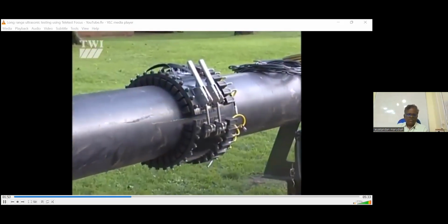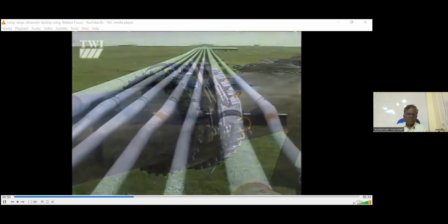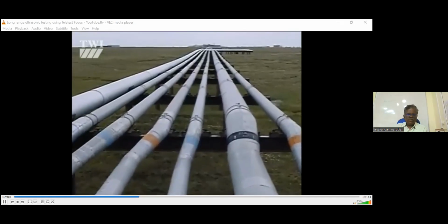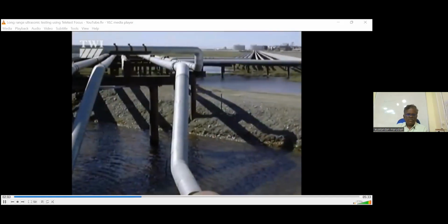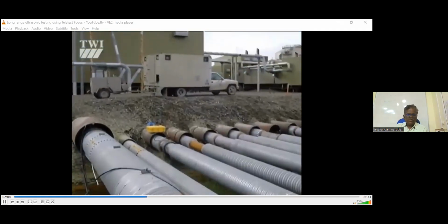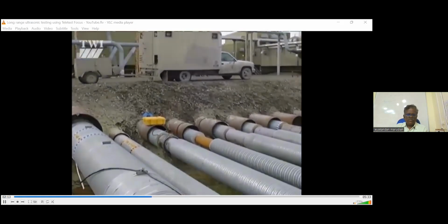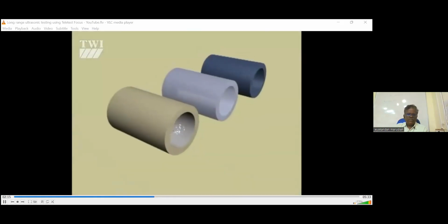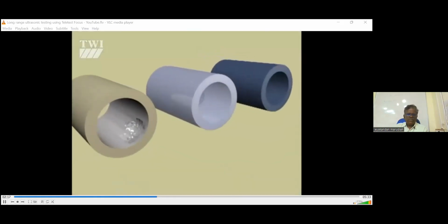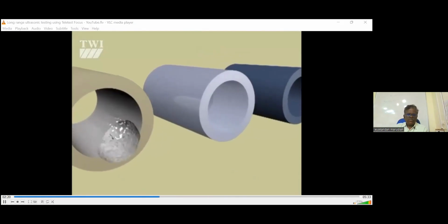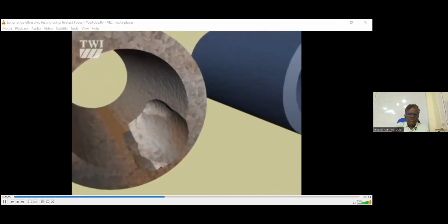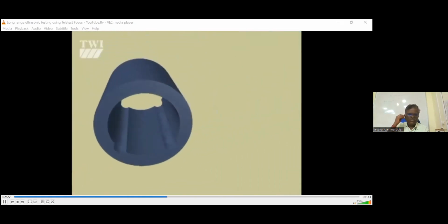What are the advantages of using this technique? First, since it's a remote monitoring system, you can inspect lengthy pipes from distant locations, typically 30 meters. Second, you can inspect inaccessible regions like clamped, encased, or buried pipe. The process provides full volume coverage and is sensitive to metal loss down to 9% or more of the pipe wall section, whether it's caused by erosion, corrosion, or, as we see here, in-service damage.